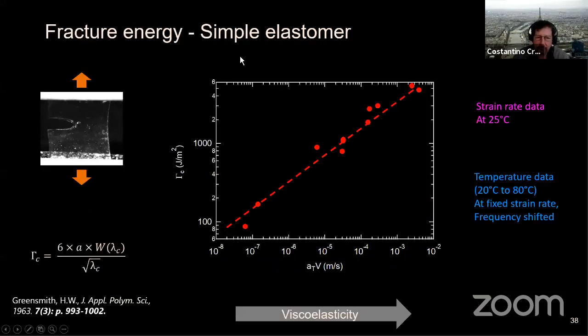First of all, if we look at the scaling of the fracture energy, we get a relatively normal scaling. Here we time-temperature shift the data. The data that is taken at different temperatures, 20 to 80 degrees, we are using linear viscoelastic shift factors to actually create a fracture master curve. And this is what you see over here. These data points have been taken at room temperature at the higher fracture energy, and the ones at the bottom here are more the high temperature data.